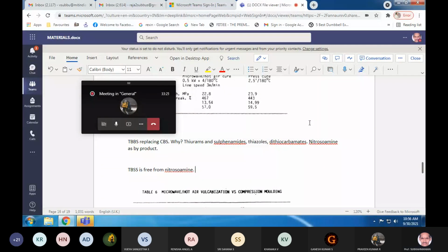What is the effect? Peptizers are used as radical scavengers. They isolate the free radical of the rubber macromolecule. That is what we require in mastication or peptizing. What the anti-ozonants do, they prevent this free radical. They rather add to the stability of the rubber chain. You understand? So that is where the antagonism is. So you have a synergism as well as antagonism.